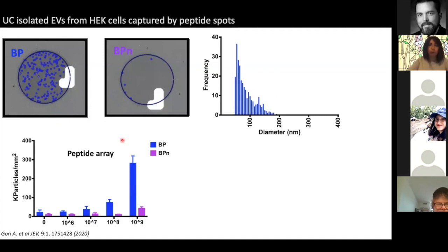Then we performed dose response experiments in which we made serial dilutions of our sample from 10 to the 9 down to 10 to the 6 vesicles per ml. We incubated this sample on the peptide array, and the blue bar reports the number of vesicles captured by the BP peptide, whereas the violet bar here reports the particles captured by the negative control. These numbers are expressed as kiloparticles per square millimeter. And you can see that looking at the dilutions, we could easily detect concentrations of extracellular vesicles down to 10 to the 7 extracellular vesicles per ml.